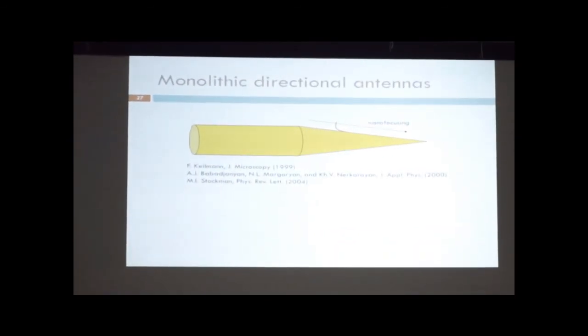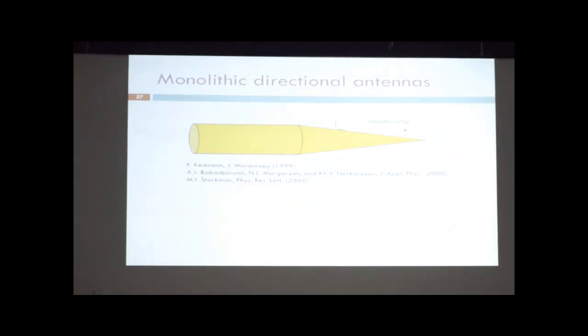So we worked on this concept and we tried to develop monolithic directional antennas based on the concept of nanocones. So let me explain this briefly. This is a metal nanowire. The metal nanowire supports surface optical modes that propagate along the y-axis. A nice property of these modes is that they don't have a cutoff. So even if you reduce the diameter of your wire, you still have a propagating mode. So if you then take the nanowire and you sharpen it, then you can get this optical energy carried up to the nanoscale. And this is called nanofocusing.